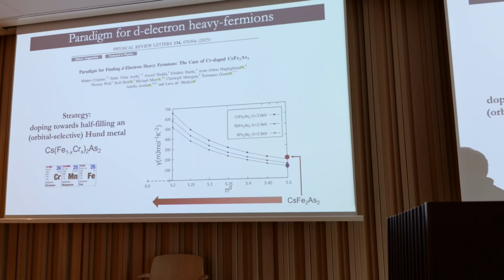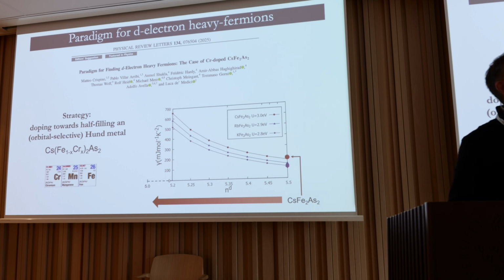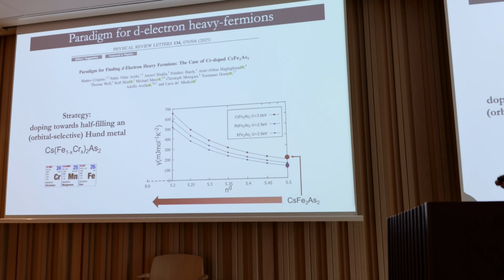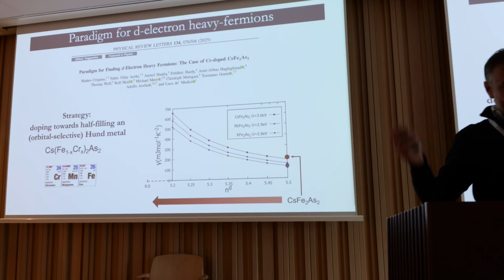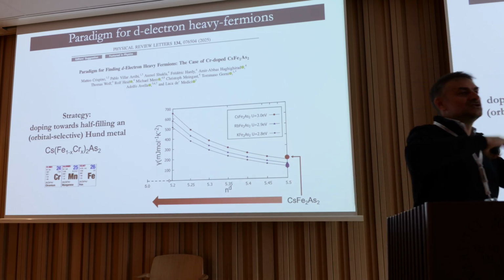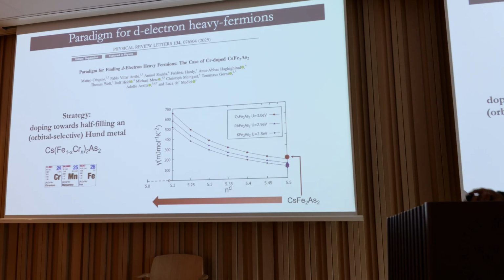Then comes the experimental part that we did with the Karlsruhe group. We said, let's take the most correlated 1-2 iron-based superconductor that we have, cesium iron-2-arsenic-2, which has an experimental Sommerfeld coefficient of 180 millijoule per mole Kelvin squared, and try to dope even more towards half-filling. How do we do that? We heard yesterday that one possibility is termination, surface doping, but here we tried real chemical doping by substitution in a bulk single crystal, putting chromium instead of iron.